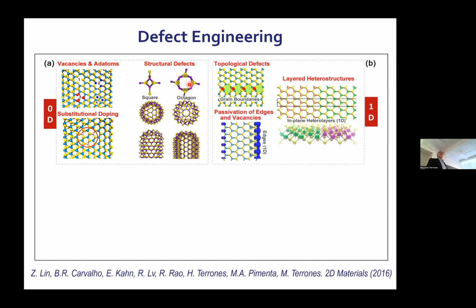Then we have what I call 1D defects, which could be the edges of these systems, right? So you have, for instance, edges of ribbons or edges of crystals. You have also grain boundaries, where you can just join. In this case, you are pushing the octagon and square-like defects in a row, and then that counterbalances the angles, and then basically you create this boundary. Or you can have stacked in-plane heterostructures, which is stitched monolayers, and then you have one material here and one material there, and then you have one big channel here.